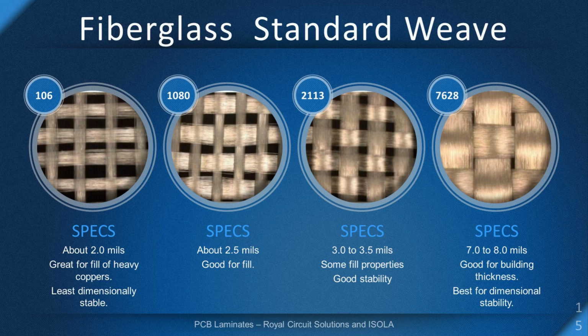All right, our second decision we make when looking at a stack up is going to be the actual type of fiberglass weave. On the screen in front of you, you can see 4 standard types of weaves. Now, your 106 weave is going to be really good for filling coppers. It's a thinner weave, so you're going to have a thinner thickness between your layers if you're only using 1 or 2 plies. As you go to the right, they increase.